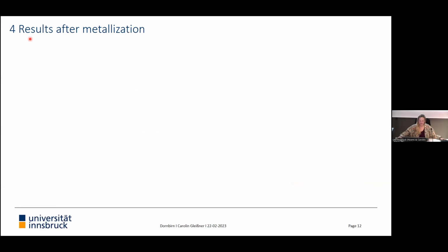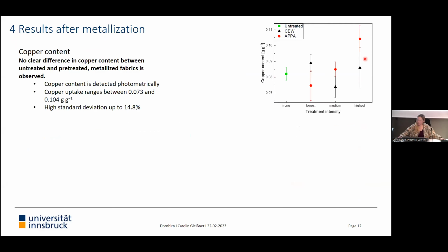First of all, I am looking at the results directly after the metallization, and looked at the copper content. As you might see, on the x-axis there is the treatment intensity, and on the y-axis there's the copper content. The green is for the untreated fabric, the red for the plasma treated fabrics, and the black for the calcium chloride ethanol water treated fabrics. You see no clear difference in copper content between the untreated and pre-treated fabrics. The copper content was detected photometrically, and these uptakes ranged between 0.073 and 0.104 gram copper per gram sample.